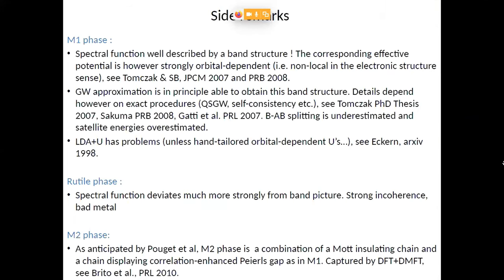Yes, perfect. Okay. So LDA plus U is actually not really getting it unless you do something insane to U. And that is actually for the same reason as we just said, even in single-site DMFT, you would need to crank up U to insane values, and then you would not get the physics because you would not have the singlet state. So that is, I think, somehow not incorporating the physics that you need, which is really this correlated dimer physics.